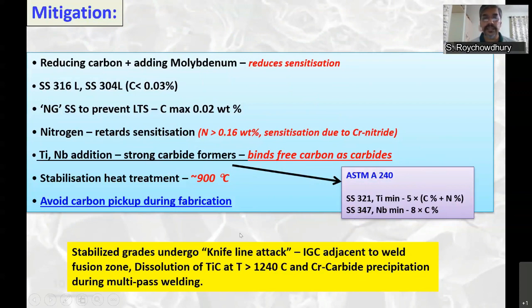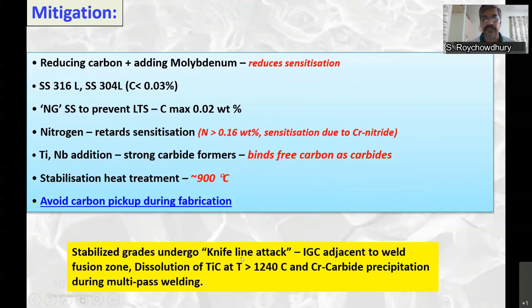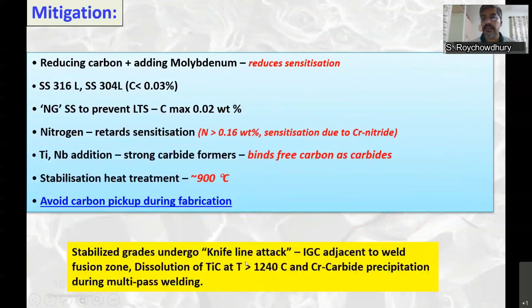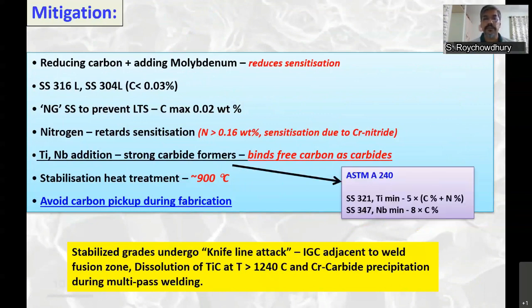They undergo another form of IGC called knife line attack, which is immediately adjacent to the weld fusion zone, as opposed to sensitization, which is at some distance away from the weld. So what happens during the first pass of welding? In the region adjacent to the weld fusion zone, where the temperature exceeds 1240 degrees centigrade, the titanium carbide dissociates and free carbon comes into solution. And subsequent multi-pass welding will lead to chromium carbide precipitation again, and again IGC will occur.